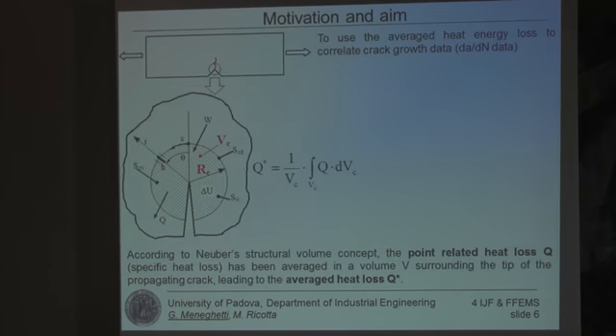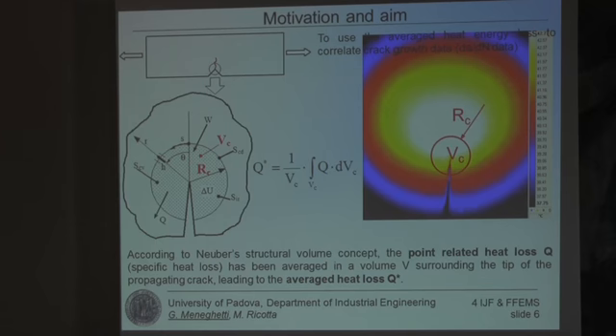Now, the motivation of the present work is to study the crack propagation from a crack starter, consisting of a very sharp notch, and we want to use the average heat loss to correlate the crack growth data. So the idea is sketched here. We use as a fatigue damage indicator the specific heat loss, but as we know that the notch becomes very sharp, or if we have a crack, like in this case, Neuber taught us that the fatigue-related quantity should be averaged in a properly defined material structural volume, where the process zone takes place. So, in formulas, we have to average the heat energy loss inside such a structural volume, so we have to perform such an integration. This is the typical situation that we observed in the laboratory tests.